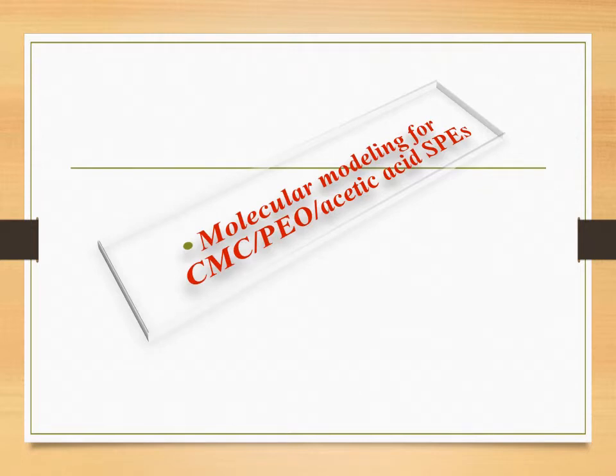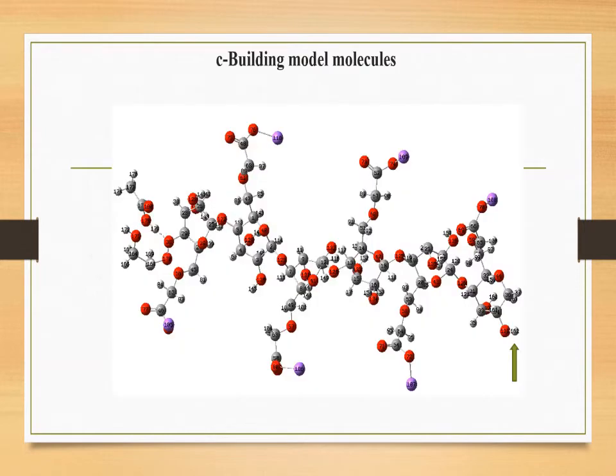Molecular modeling for CMC/PEO/acetic acid solid polymer electrolyte material. As we saw from the previous slides, the model molecule representing trimer CMC with monomer PEO possesses the highest total dipole moment and the lowest HOMO-LUMO band gap energy, so we can increase our levels of calculation by adding acetic acid to this model molecule in order to increase the reactivity and enhance the electronic properties more.